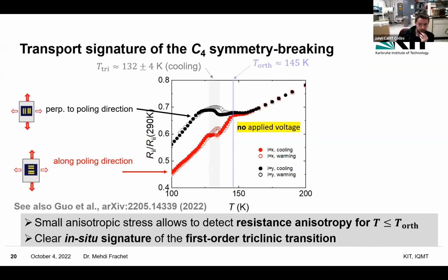Okay, so is the reason why this is different from a traditional regular measurement that it's sitting on the piezo stack, which is applying some strain even with no applied voltage? Yes, I think what is happening is that you have some orthorhombic domains, which is also partially at least why we observe this hysteretic behavior. When you glue it to the piezo, you partially detwin the sample. That's probably what is happening. Got it. Okay, thank you.